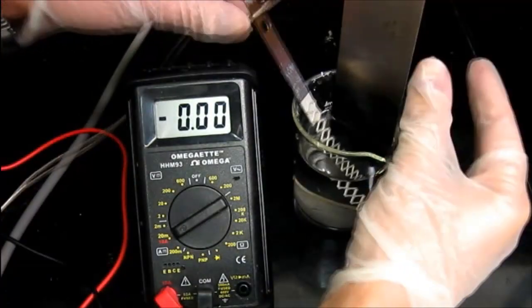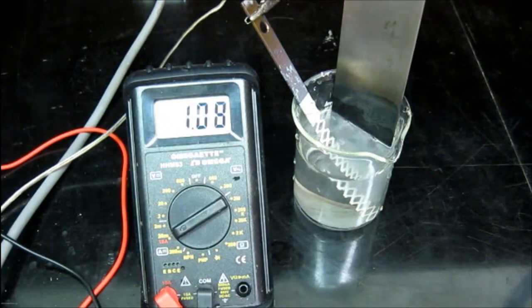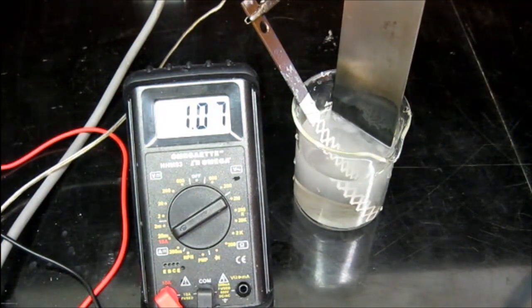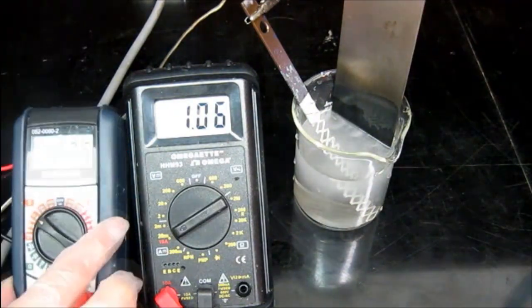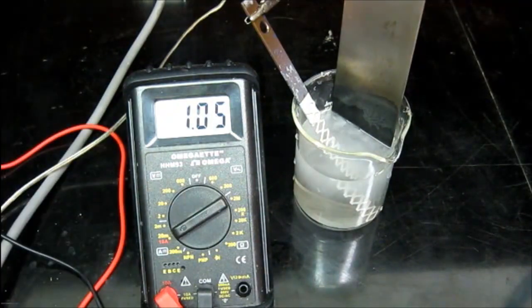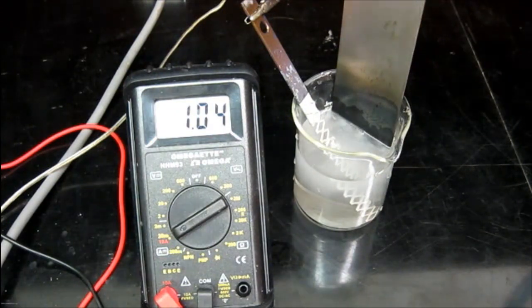Here I'm using it to electrolyze a dilute solution of 5% sulfuric acid, and as you can see, it doesn't passivate like pure titanium. The cobalt oxide on the surface is electrically conductive and serves to transfer electrons from the titanium to the solution without creating an insulating titanium oxide layer. Now this would be great if cobalt oxide lasted forever, but unfortunately the cobalt oxide is slowly decaying. Eventually this will passivate once the cobalt is gone.